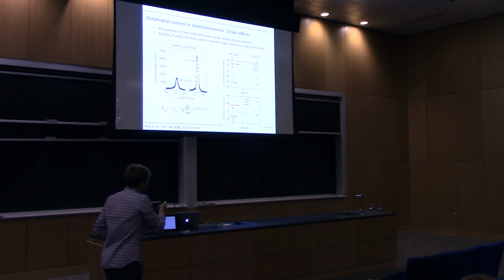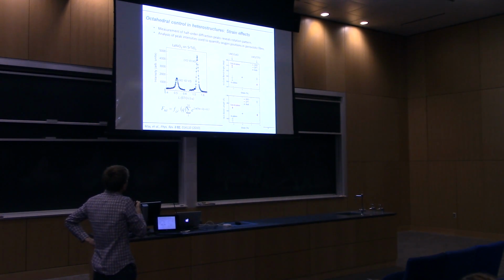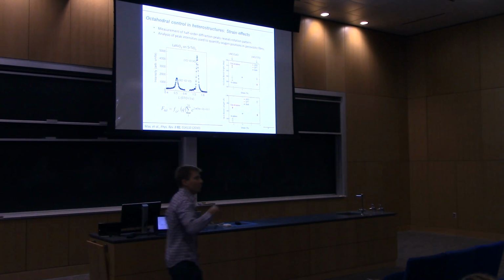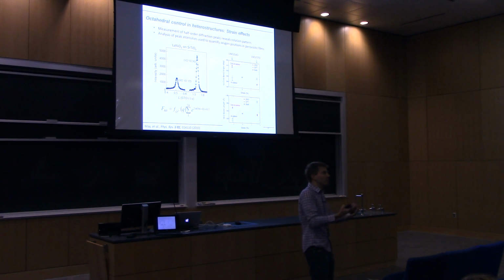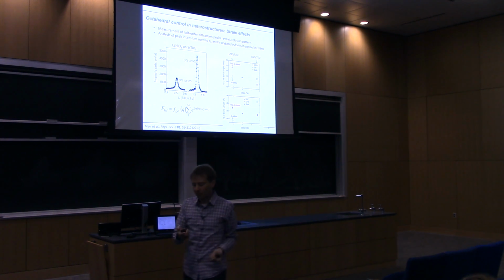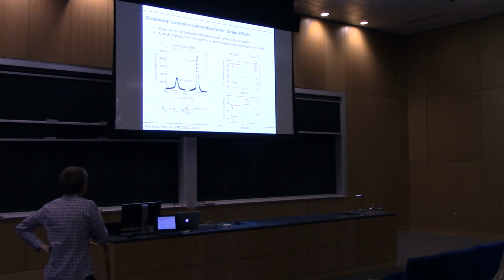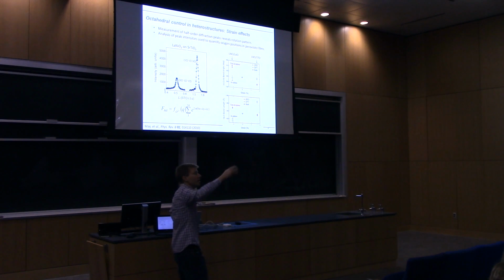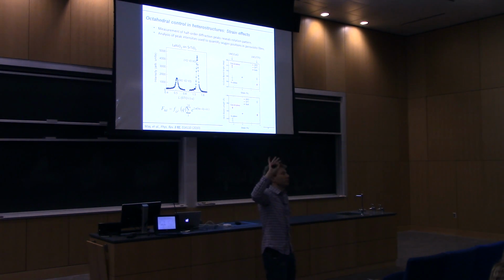Okay, so quickly, just one slide on strain, and also to introduce this idea of how we measure these in thin films. In bulk, people do powder diffraction, but in films, we don't have that. We can't do that on a single crystal 10 nanometer thick film, right? So we have developed this technique using synchrotron diffraction, where we measure these half-order diffraction peaks that come from this unit cell doubling of the octahedral rotations.